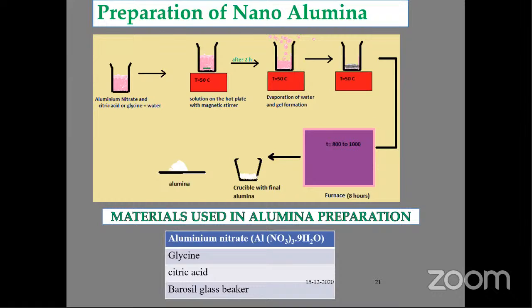As I said, alumina is available in two forms, gamma alumina and alpha alumina. If you burn at 600, 700 or 800, then the alumina formed will surely be gamma alumina. From 800 to 1000, you will get alpha alumina, which is a pure form of alumina, a pure ceramic. We can vary the parameters from 800 to 1000 and check, at the lowest temperature, what best alumina we can get, when you are developing that alumina. So we can vary it in the furnace from 800 to 1000. After that, we'll get pure alpha or gamma alumina.